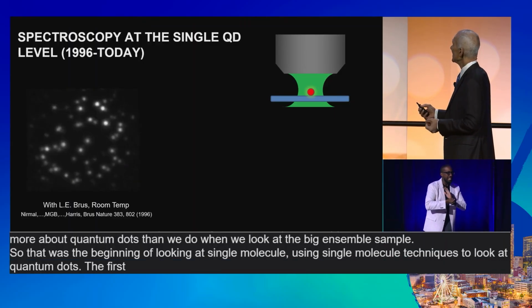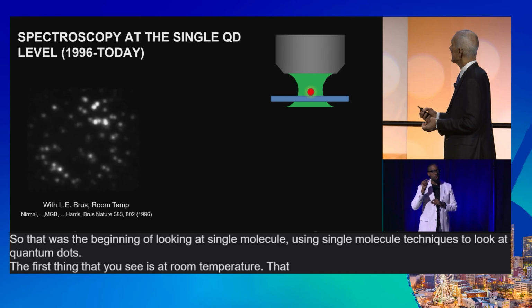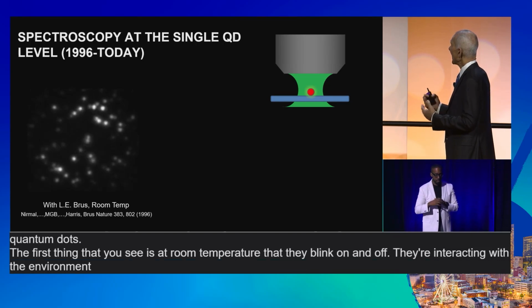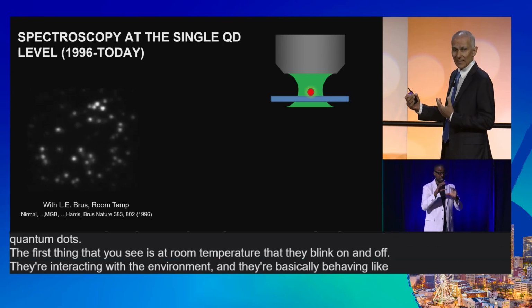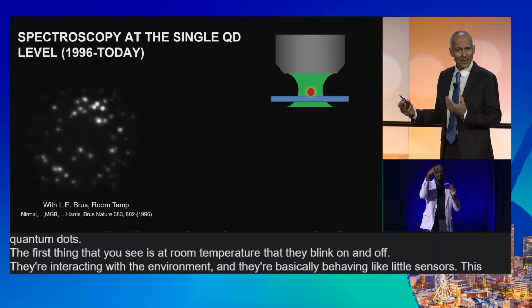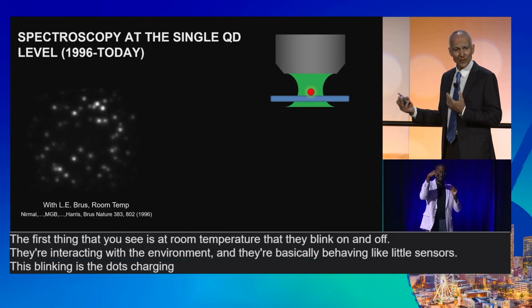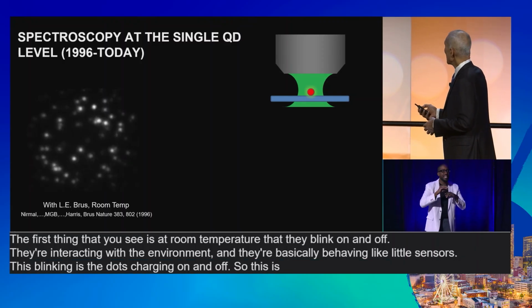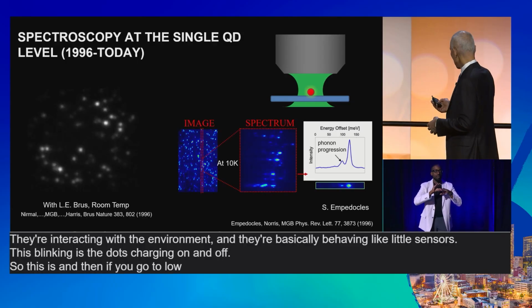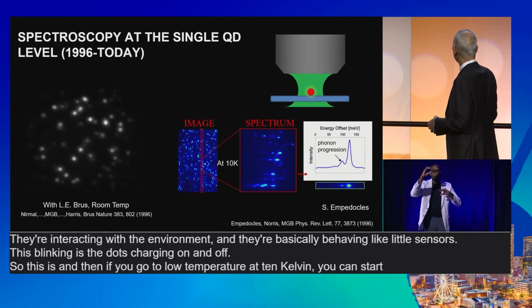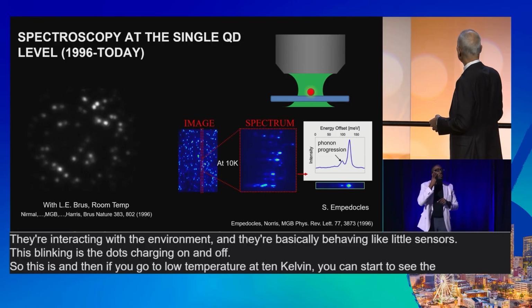And the first thing that you see is at room temperature that they blink on and off. They're interacting with the environment, and they're basically behaving like little sensors. This blinking is the dots charging on and off. And then if you go to low temperature, at 10 Kelvin, you can start to see the spectrum of an individual quantum dot.